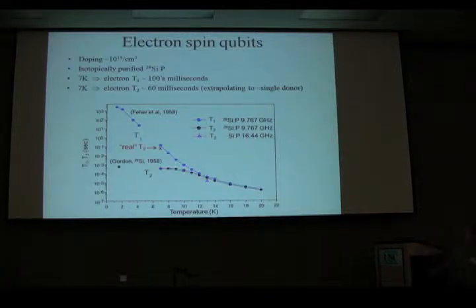This is actually some old data. We were first starting to work on this. And what we have here is just T1 and T2. So the blue is T1 as a function of temperature. And this is data that Feher had taken in the late 50s. And here is some pulse data that we'd taken on T1. And you can see it gets up an hour or something at one Kelvin. But in fact, in the very first microwave spin echo experiment, Jim Gordon measured T2 of phosphorous donors in silicon.